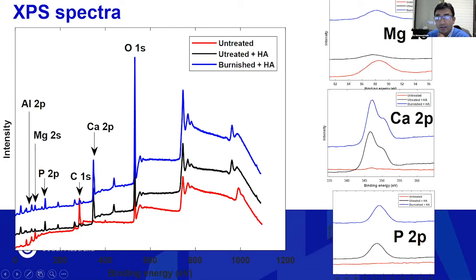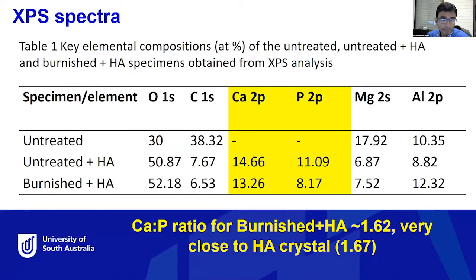We can see there is only a little presence of magnesium in the case of the untreated plus HA coated surface, because the HA coating has covered the substrate. But in the case of the HA coated surface, either untreated plus HA or burnished plus HA, you can see a large peak of calcium, which indicates the presence of calcium. And similar to calcium, we also have the phosphate element present in our XPS spectra. So this is another confirmation of the deposition and successful formation of the HA crystal.